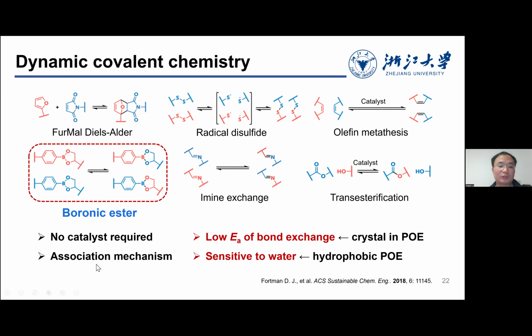And another good thing is that the boronic ester groups have almost no activation energy for the bond exchange. That means they are not stable. But the thing is, if we have crystals in the POE, maybe they can help to increase the activation energy of this kind of bond. And another thing is this kind of group is highly sensitive to water. But the good thing is the polyolefin elastomers are pretty hydrophobic. In another way, they can protect this group when it is embedded into the network.